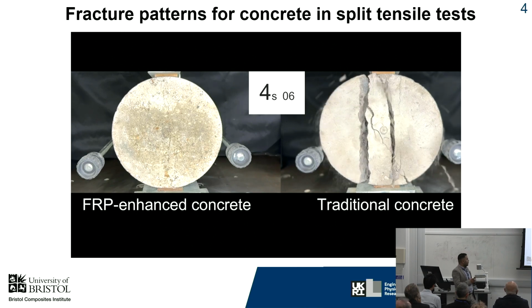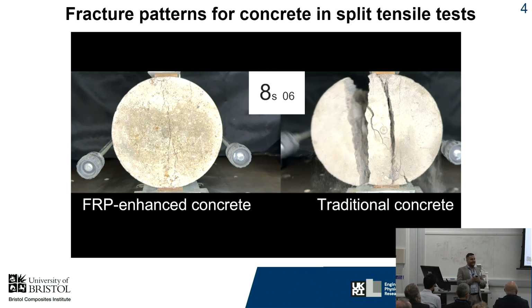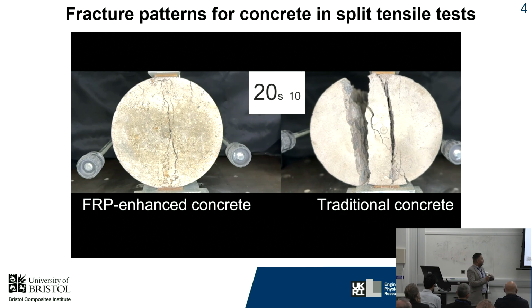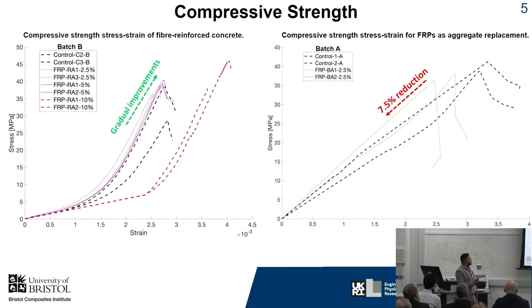The fracture pattern for split tensile is really important to see, the difference between both of them. The traditional concrete split in half immediately, after a couple of seconds, while the FRP-enhanced concrete literally keeps the concrete mixture together in one shape. That will help with earthquakes, or in anything requiring split tensile strength, such as bridges. Now moving to compressive strength.